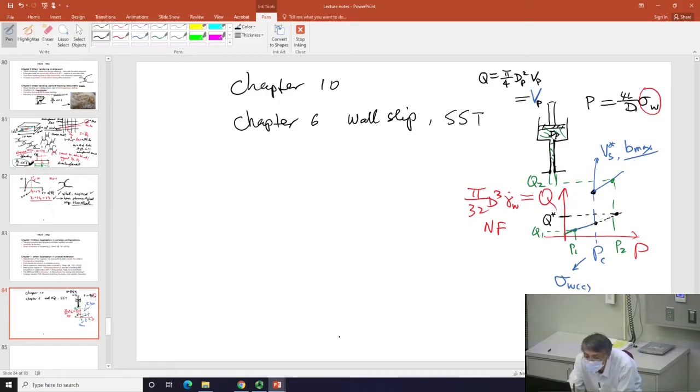In other words, remember I told you when you use rate mode, you can lower your pressure, it will still stay on this upper slip range until some moment. So the reality is actually very trivial. You have a parabolic profile initially. It tried to deform like this. And all of a sudden, that pressure is too much. It will slip, which means it will slip like this, and then the middle sheared very little.